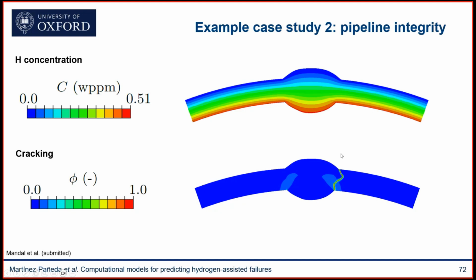And basically what we want to do here is we have two scenarios. One is what we call plastic collapse, so a situation where you get complete yielding of the pipeline before cracking. This is what we want to have. And the other one is a situation where you have brittle fracture before this plastic collapse scenario happens. And what we do is we increase the pressure until we see this brittle fracture happen, so we can quantify the critical pressure at which you can transport hydrogen in existing natural gas pipelines.